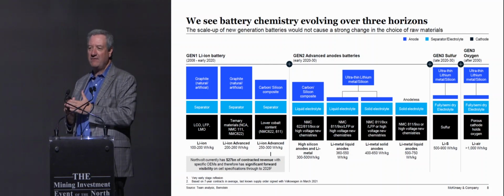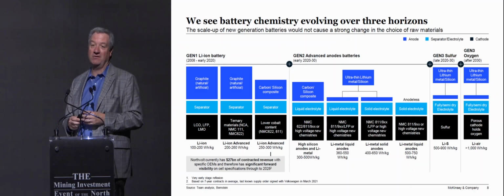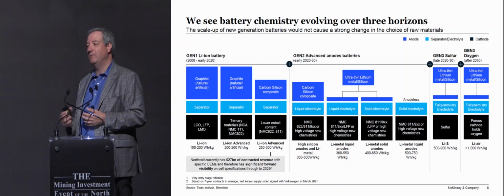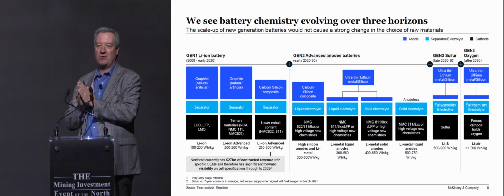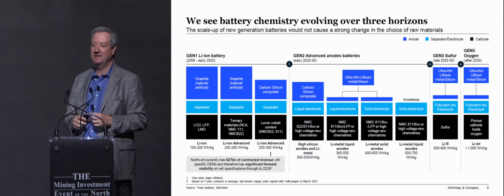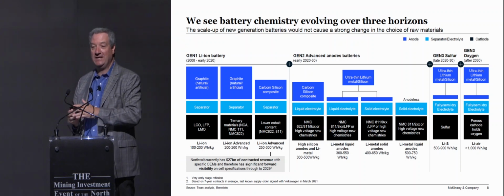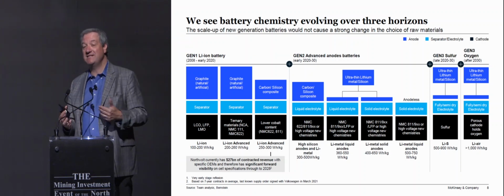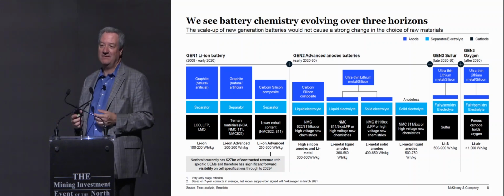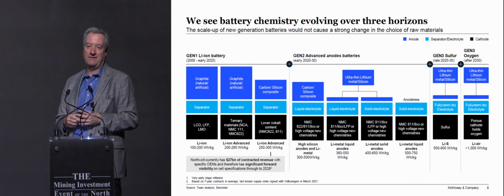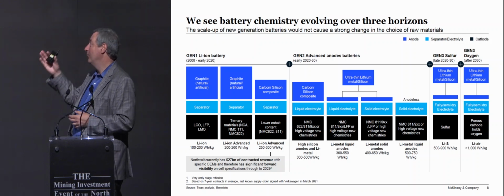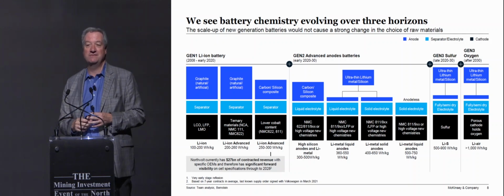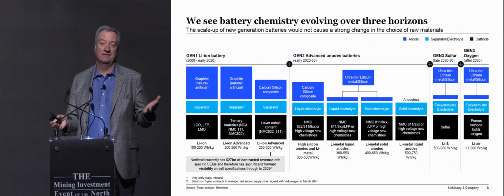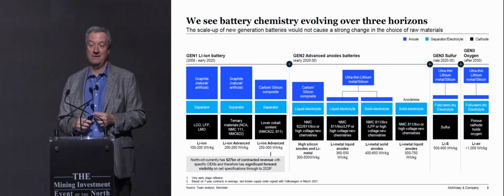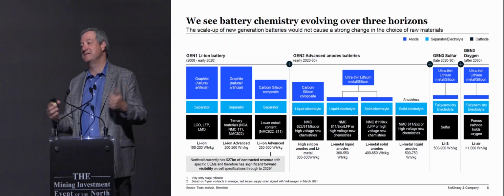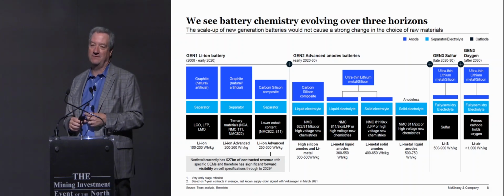So the thought was, how can I really hold that lithium in there so it doesn't degrade? Solid state was thought to be a way to do it, where you put a solid on one side and a lot of pressure on the other, keeping that lithium completely tightly wound so it can't degrade. But there are new technologies called semi-solid state, which don't use solids, but use a polymer around that lithium metal. With lithium metal, you can start to talk of densities double today's batteries. And then there are batteries we call lithium sulfur, which talk about triple today's density, but they seem a little bit further down the line.